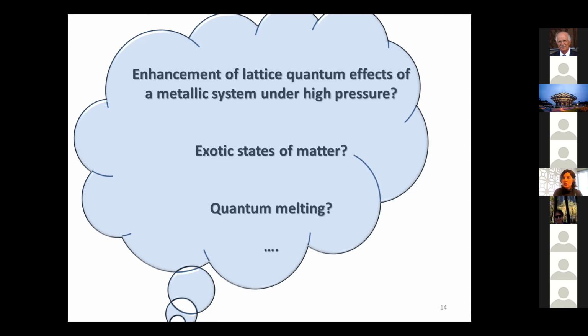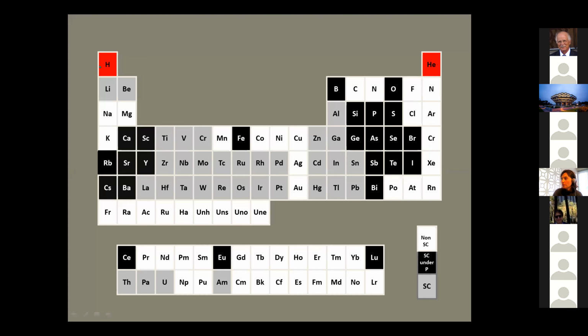So basically, based on the definition of the Boer parameter, we're looking for low mass materials that have these long range interactions, and they maintain them over a high range of pressures. And obviously the best case would be hydrogen, because hydrogen supposedly becomes metallic and is extremely light. Helium is not very helpful because it's true that it's a quantum solid at ambient pressure, but it remains non-metallic as far as we know. Hydrogen, on the other hand, becomes metallic, but the pressures are extremely large. It's 0.5 terapascal. And how to really look at the material properties is a challenge that the high pressure community has to address before we get to hydrogen as a material to study for these quantum effects.